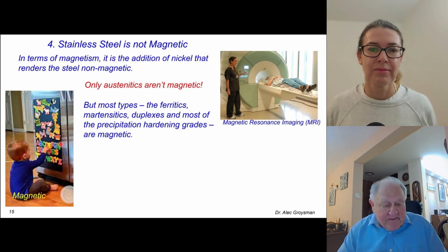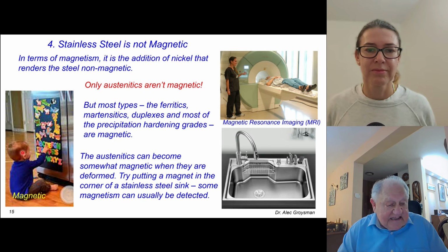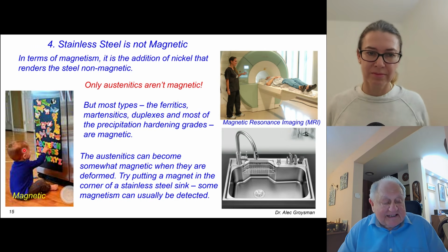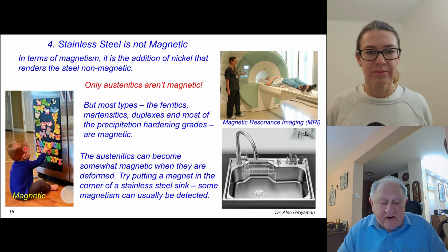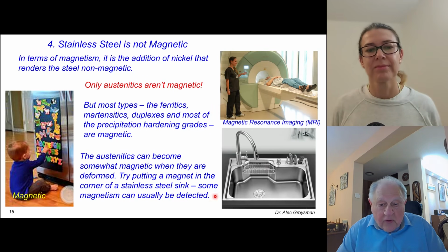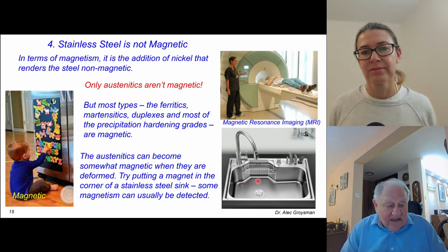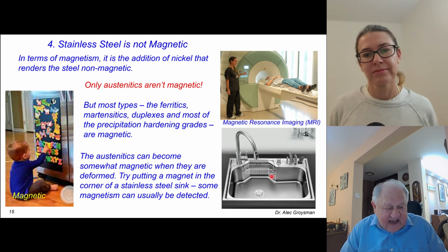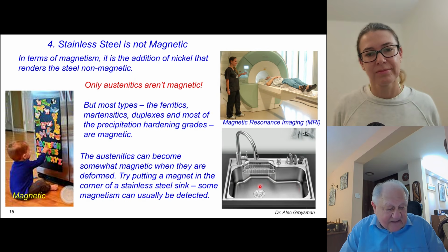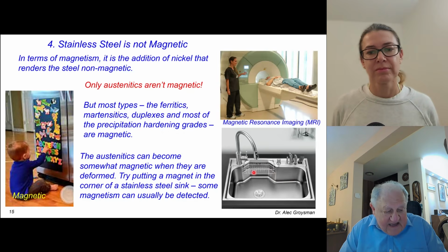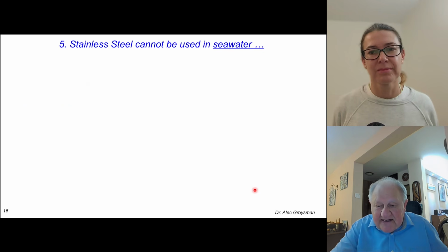Let me share my personal note. Austenitic stainless steel is in a natural, unusual metastable condition. At room temperatures, ferrite is stable. The addition of nickel and manganese makes austenitic steel stable at room temperatures, but the austenitic can become magnetic when it is deformed. Cold work and welding are liable to increase the amount of martensite and ferrite respectively in this steel. After deformation, it is work-hardened steel. Try putting a magnet in the corner of a stainless steel sink. Some magnetism can usually be detected.